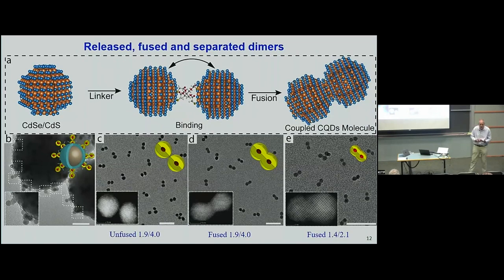Size-selective precipitation with a solvent-non-solvent consideration is very good for this because the difference in volume between monomer and dimer is really large. So that easily separates, and you see a purified version. This is the non-coupled version bound with the organic linker. In this one, I will not have the strong coupling that I'm looking for, or essentially will have weak tunneling effects. I can still have energy transfer and so on.